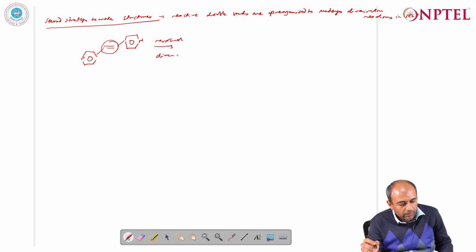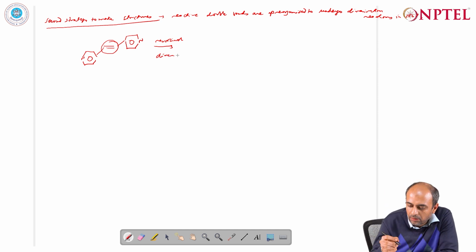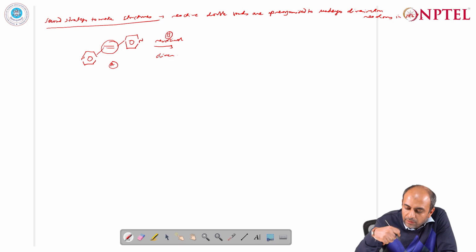And what is done essentially is we take a stoichiometric amount of A and resorcinol B. We do the process of mechanochemical grinding where we mix the reactants in a mortar and pestle, and when we grind it for an hour and a half, the resulting solid state phase which is obtained is then crystallized.